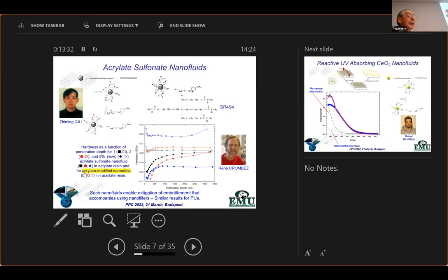these materials form insoluble salts, but when you replace, let's say, the chloride with a big soft anion, this turns these things into room temperature liquids, or perhaps very sticky, extremely high viscosity liquids. So this can be tuned from olive oil to gel. Okay, so here we have just an example of taking this material and making a resin with this tetraacrylate monomer.